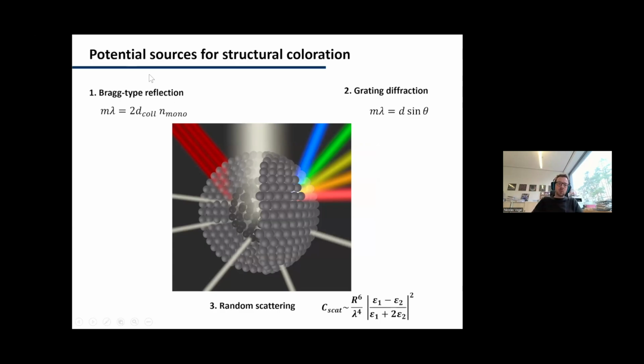The first, what we typically want, is a Bragg type reflection, so that light is reflected by all these individual layers and then comes out, depending on the size of the layer, in a certain wavelength that's being constructively interfered. But we can also observe grating diffraction effects, so an effect from the surface. And if we don't have perfectly ordered superparticles, we always have scattering, incoherent scattering, so white light, by defects and irregularities, which are typically found in the middle of the structure.